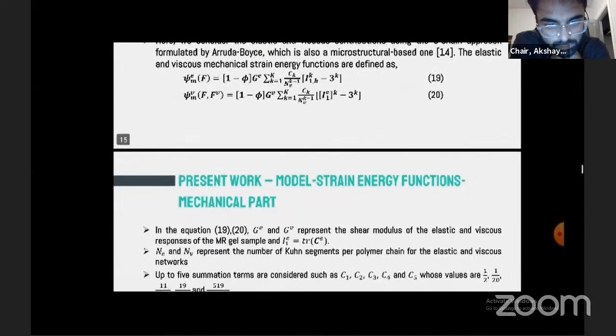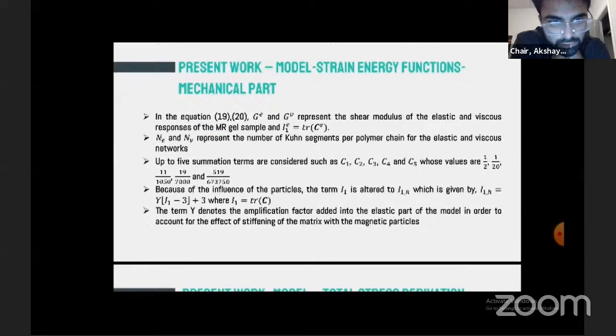In equations 19 and 20, Ge and Gv represent the shear modulus of the elastic and viscous response of the MR gel sample. Ne and Nv represent the number of Kuhn segments per polymer chain of the elastic and viscous network. Upon summation, since the influence of the particles is higher, I1 has been altered to I1H, which is written as Y times (I1 minus 3) plus 3, where I1 is the trace of the left Cauchy-Green tensor.